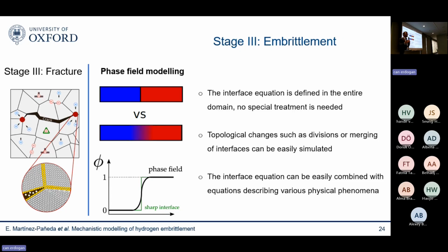And the other one is the computational challenge. How are we going to couple this evolution of cracks through a component computation, right? These are interfaces, these are discontinuities. And for that, we use these phase field models that have been used in many science and engineering problems. The idea is quite simple. You overcome all the mathematical and computational challenges that come with tracking discontinuous interfaces by smearing that interface over a finite domain and using an auxiliary variable, the phase field, to tell you where the interface lies.